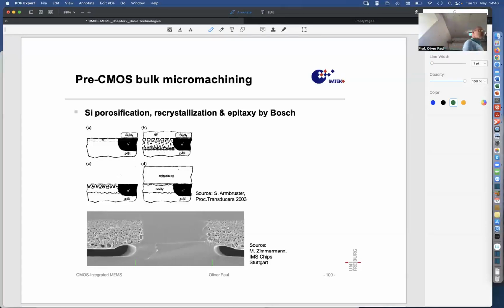And so this can also be done with silicon. Porous silicon is well known. It is done in a hydrofluoric etchant with a counter electrode, silicon being the electrode put to a potential, and then a reference electrode also in this 3 electrode setup. And then by applying appropriate voltages, the silicon is not etched as a planar surface, but it is porosified. And that also depends on the doping of the silicon.